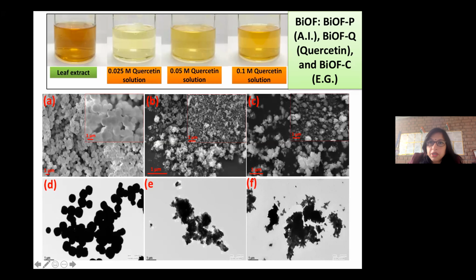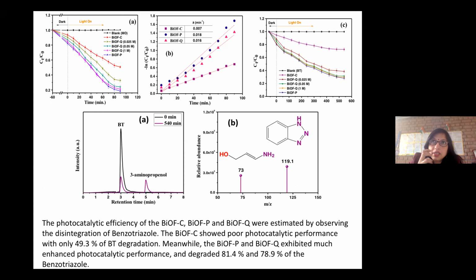So we found that quercetin has approximately equal photocatalytic activity as the leaf extract. Here we proved that by these experiments. This is the blank one, then this is the chemical one, which showed the result. Then for the quercetin, when we took different concentrations, we found 0.1 molar is the optimized concentration, and this is approximately equal to the plant extract.